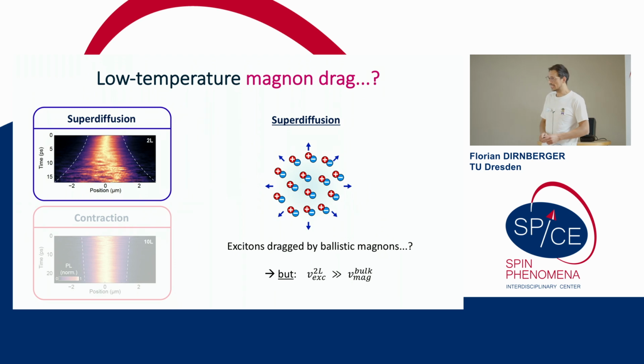However, in order to make that explanation work, we really have to understand a bit better the properties of magnons in two layers, because the velocity of excitons that we see is so large that it exceeds the velocity of magnons in bulk crystals of chromium sulfide bromide by about an order of magnitude. So we really have to understand better what it means to have magnons in a bilayer crystal compared to a bulk crystal before we can make solid conclusions about this magnon drag in two-layer crystals.